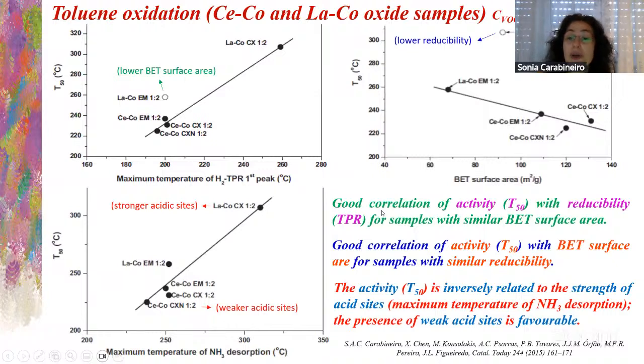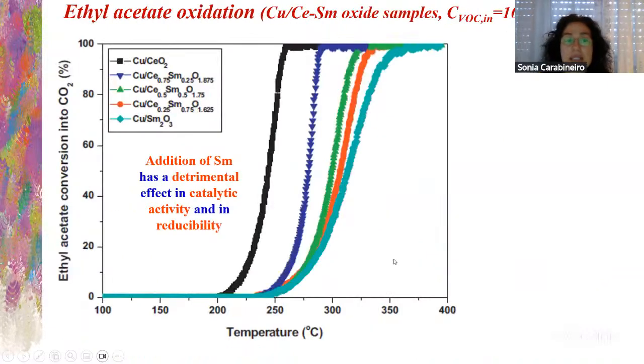And here we also obtained a relationship, an inverse relationship between the catalytic activity and the strength of the acid sites. Okay, so we see that weak acid sites are favorable. So you see there, weaker is better, stronger is worse, but there is a correlation. So that was an interesting result.